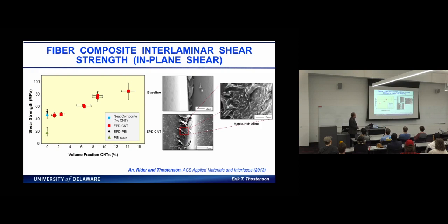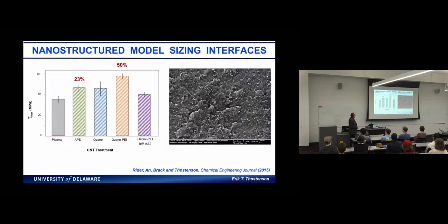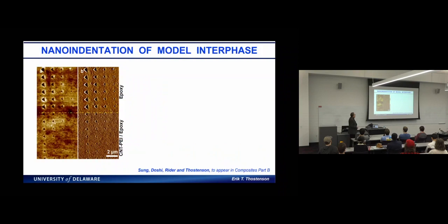This is some work we did almost over 10 years ago now, but we've really expanded this to look at the microscale interface. And what we're seeing is a very significant increase in that strength just by this chemical functionality. And we're not adding a lot of material. We're adding just a few milligrams of the material onto a fairly large piece of fabric. And we've done a lot of studies. This is something that is actually just under submission, where we've looked at modifying the interface.